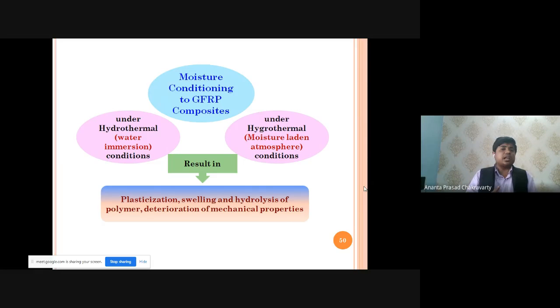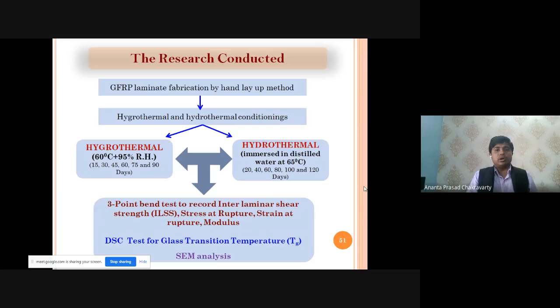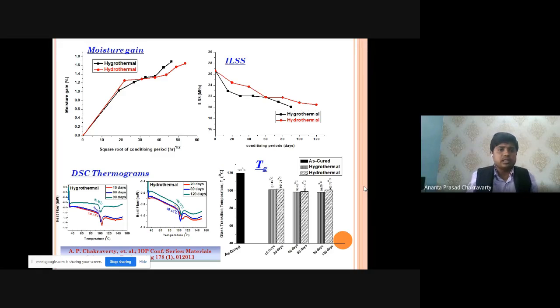Okay, in that temperature, I expected these effects like plasticization, swelling, and hydrolysis, so that the polymer can be deteriorated. So I have exposed the materials to these environments, and I have studied their mechanical property, thermal property, and microstructural property. See, moisture gain will improve, and after certain days of moisture, it has a plateau trend. That means a constant trend, so that up to that level of moisture, the decrease of strength can be tolerated up to the design stress levels.